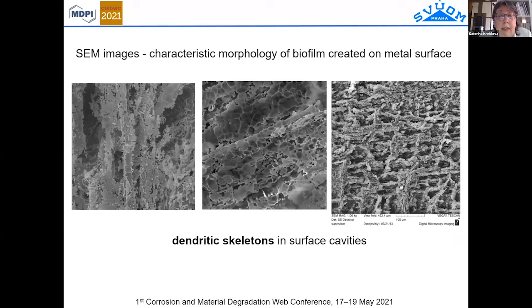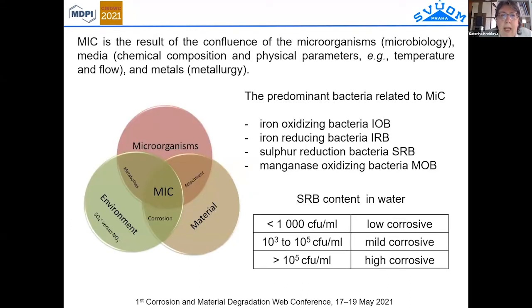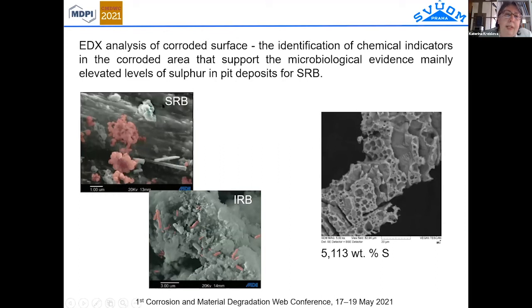What is very characteristic for cases of microbiologically induced corrosion is the presence of dendritic skeletons on the surface. It's a residual of biofilm which was created on the metal surface. And as I mentioned, we also look for the concentration of bacteria. We test the number of colonies, and there are some limits which give us information how corrosive the system is. The analysis of the surface gives us information about the presence of bacteria and of sulfur on the surface.